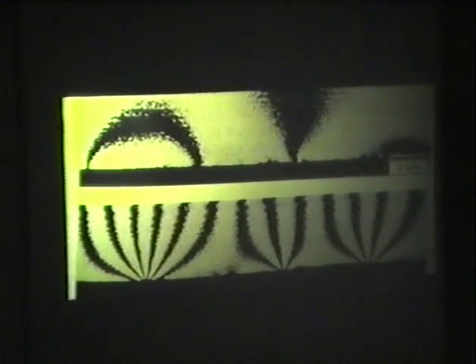Okay, so suddenly we began to have an industry of superconductivity, and here's a picture of one of the early practical superconductors which could generate quite strong fields. It was found that with the pure metals, all you had to do was contaminate them with things, and they turned into this type 2 material with this vortex state.